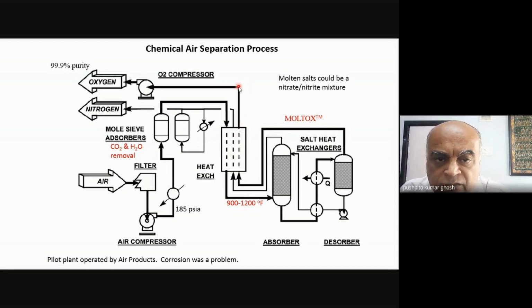So from this one, you can see that you get oxygen out, and you can compress that oxygen. You can make oxygen cylinders out of it, and it's high purity, 99.9%. Nitrogen has no affinity for this; only the oxygen has affinity for the molten salt. Whatever nitrogen came out, that's your nitrogen. Many times, the purity of the nitrogen is also quite good, and you might be able to make use of that nitrogen. But usually there will be some amount of oxygen present, so the nitrogen may be treated more as a waste, rather than as a useful product. But this is in sum and substance the sort of thing that you do based on solubility.